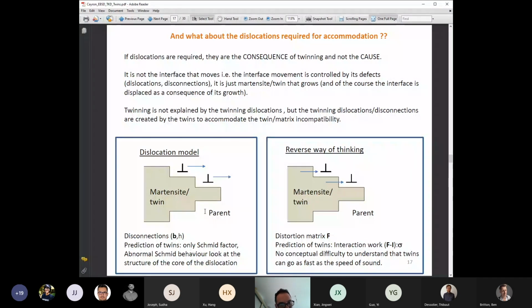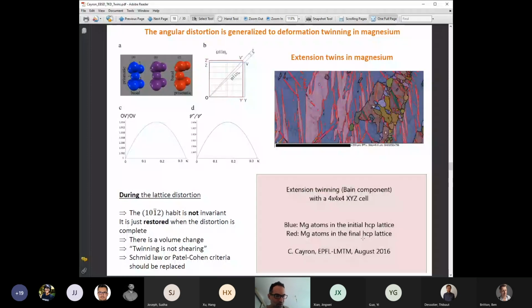So when people show some dislocation at the tip of a martensite or at the tip of a twin, and that tells that these dislocations have created the martensite itself, I said, no, I disagree. To me, it's the martensite or the twin that has created the dislocation. So you have to reverse the classical way of thinking things when we use dislocation. And the good thing is that by changing this way of thinking, we can now look at many different problems.